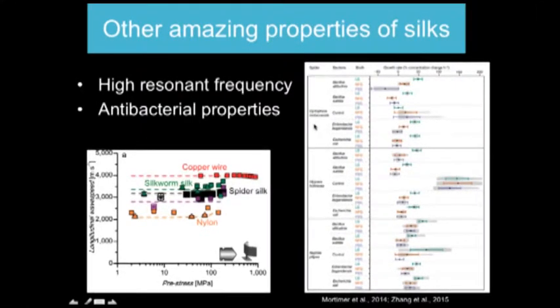Other interesting properties from dragline silk are the antibacterial properties exhibited and recently shown by our laboratory. If we look at this graph, I know it's a little bit complicated, but the basic thing to understand is that we used silk from 3 different spider species, and these are species that live in different habitats, produce different kinds of webs, and potentially eat different kinds of prey. And when we expose them to different bacteria, we use 4 different bacteria, and then we use different experimental groups where LB and PBS are just positive and negative controls.